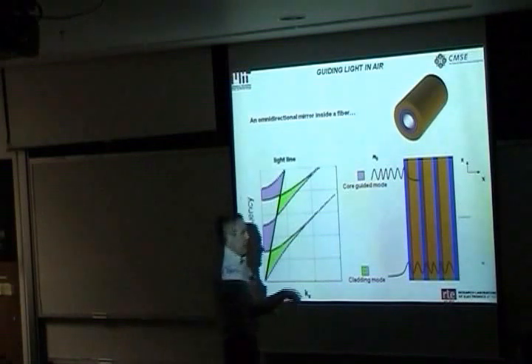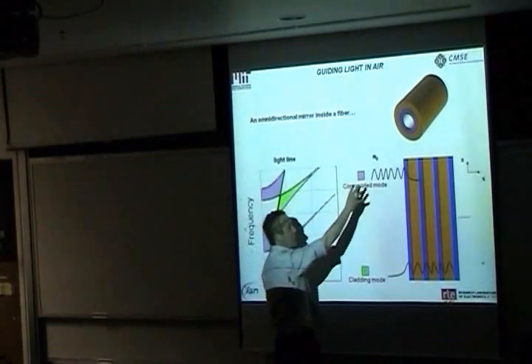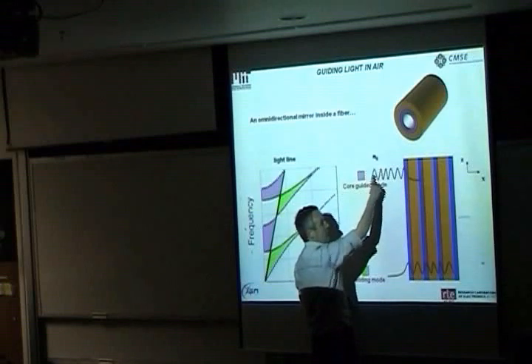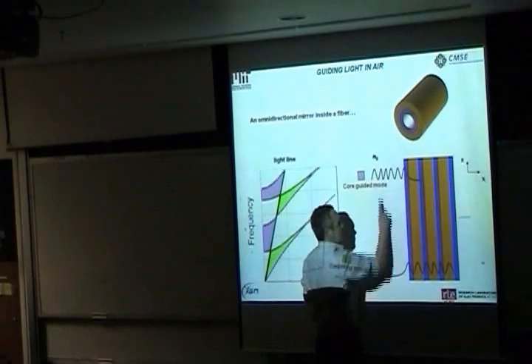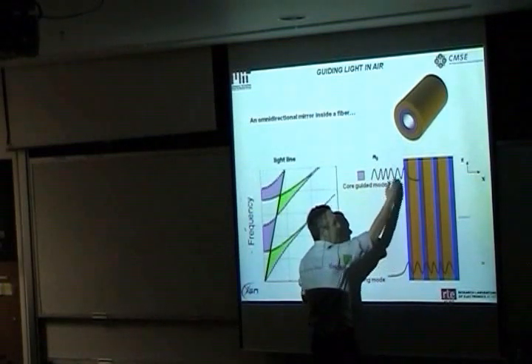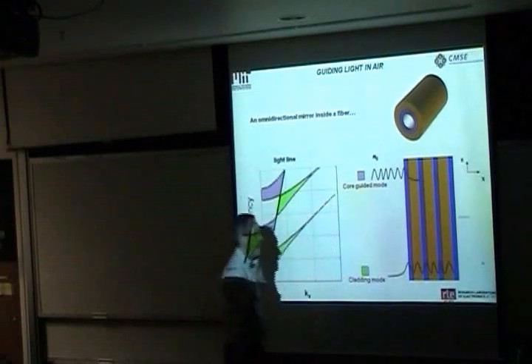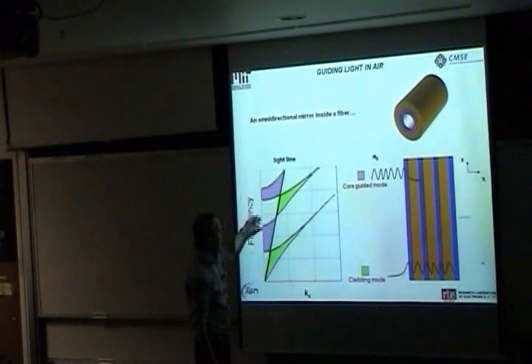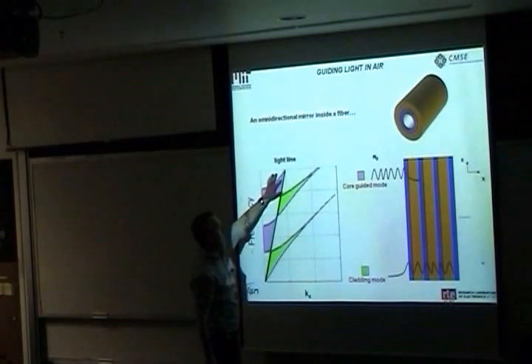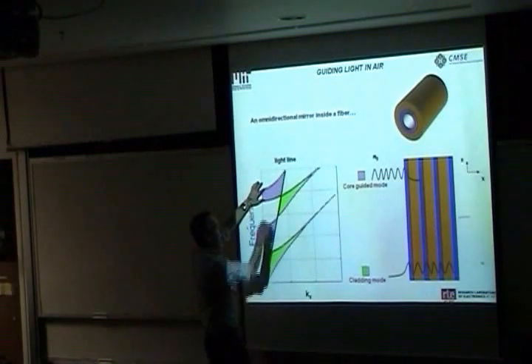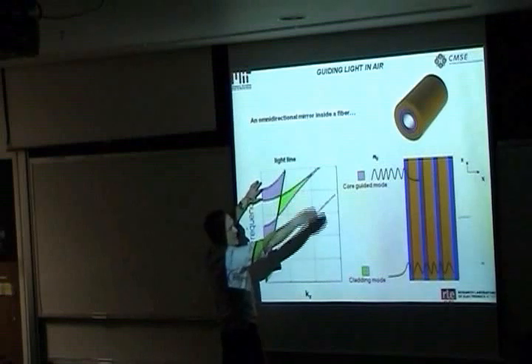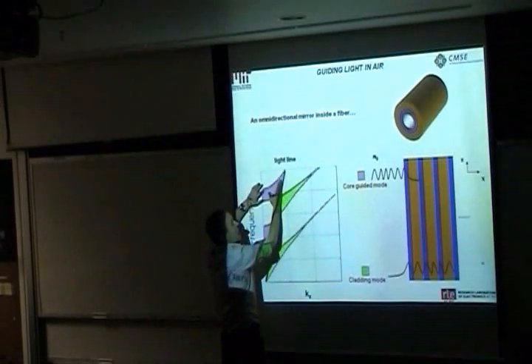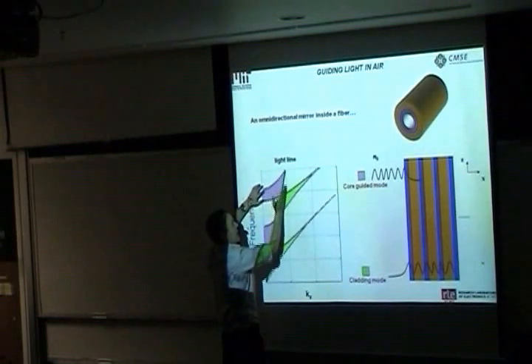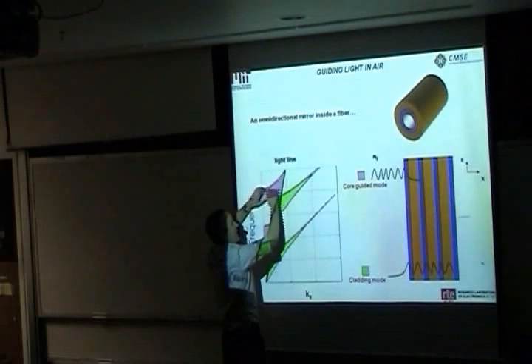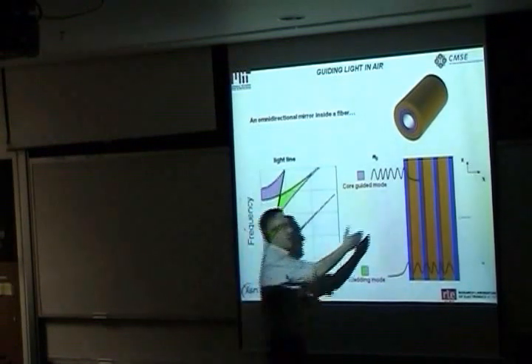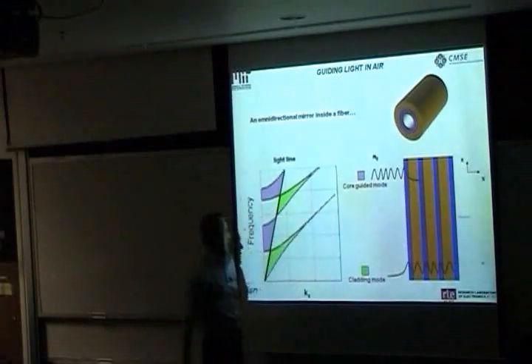So first of all, there would be core-guided modes. These are modes which are propagating in the core, in the z direction, and evanescently decaying into the structure. These are essentially the modes here in pink. They lie within the band gap of this periodic structure and above the light line. That means they're propagating in air, they're above the light line, they're within the band gap, so they actually don't leak out. They're evanescently decaying into the structure.